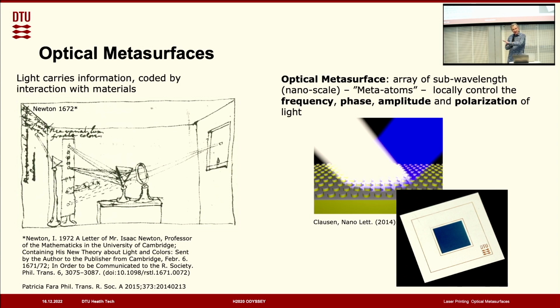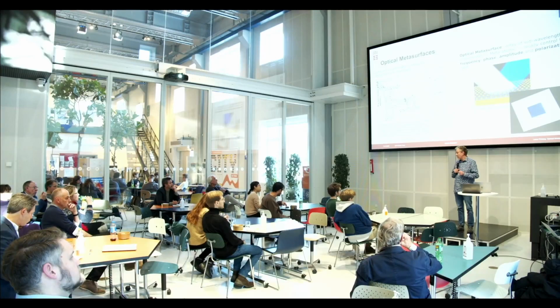And this is this surface of plastic, which has been covered with a very thin film, in this case of aluminum. So you can see that in the parts in the periphery, where it's aluminum on a flat surface, so that's a mirror like we can use when we shave, and then when the same thin layer of aluminum is deposited onto our engineered nanosurfaces, then the surface becomes blue, or appears blue, or appears red, or whatever color in this case we want.